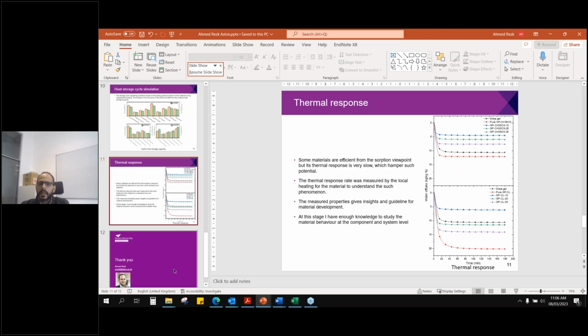So here actually is another form of investigating how the material will respond to the temperature. So we used the local heaters in the equipment to locally heat the material itself, which represent what happens in the heat exchanger in the reactor. So we can see actually the response towards heating at least. Cooling might be challenging, but heating, we can get away with heating and can draw a good conclusion out of it.